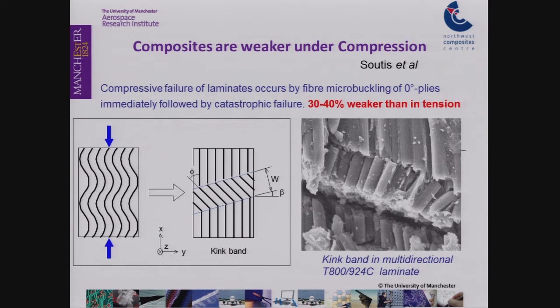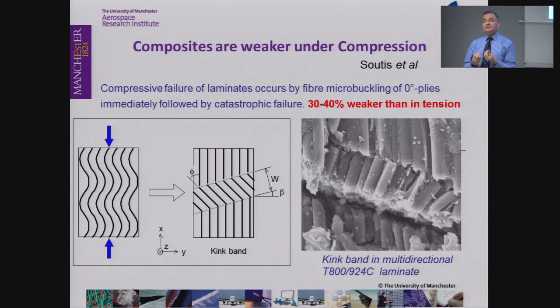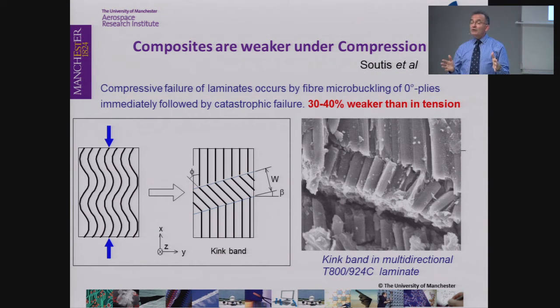And of course, the other big problem we have currently with carbon epoxy systems is that when they're loaded in compression, the compressive strength is only 60%, 70% of the equivalent tensile strength. And the reason behind it is because there is a huge mismatch in thermal properties between the carbon fiber and the polymer. So if you look at the coefficient of thermal expansion of your polymer, of your resin, is about 70 to 80 microstrains per degree Celsius, while the coefficient of thermal expansion of your carbon fiber is -5 microstrains per degree Celsius.